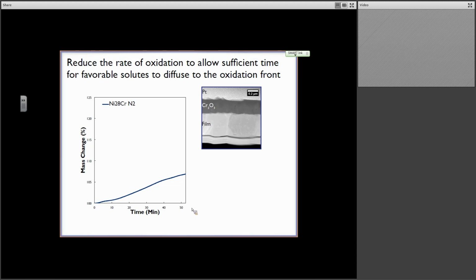So I'm showing you here TGA data, or thermogravimetric analysis data, plotting time versus the mass change. So the slower the mass change, the better the oxidation resistance. In this particular case, I have a nickel-chromium composition, and I'm going to oxidize it under nitrogen. So it's not really purified nitrogen, there's a little bit of oxygen in there, and we can see that as we heat it up to 900 C, the mass changes, and we generate a microstructure that looks like this. So this is my original metal film, and I have a nice, dense, continuous oxide forming on top. The chemistry hasn't changed. There's no aluminum in here to form aluminum oxide, so that's fine.